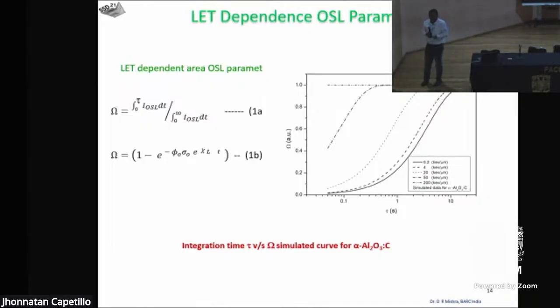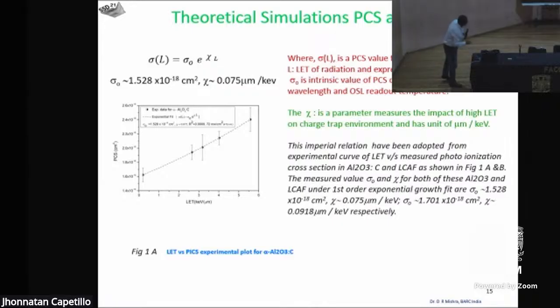Perhaps the defect environment itself is changing very rapidly. It's changing the bonds, it's changing the structure of the defect itself, and its electrostatic scenario. Now, for aluminum oxide we have measured and found that this coefficient, which is termed the coupling of LET, says that if you want to measure a broader LET range, we want an OSL material with high sensitivity but lower cross section.